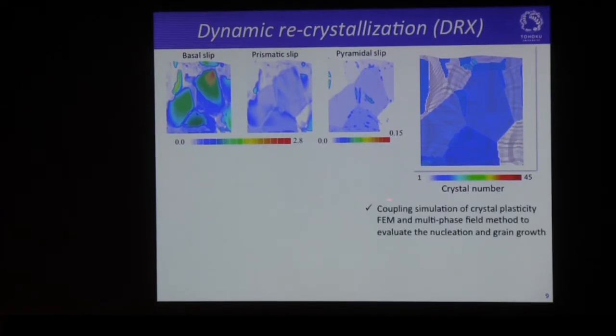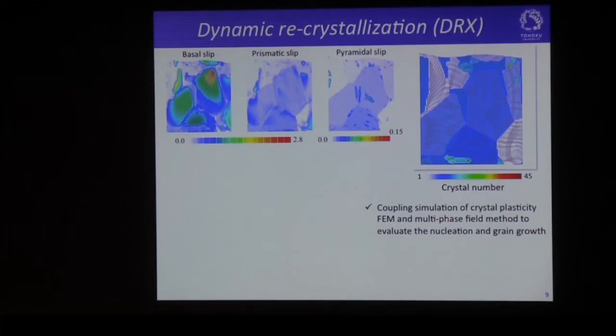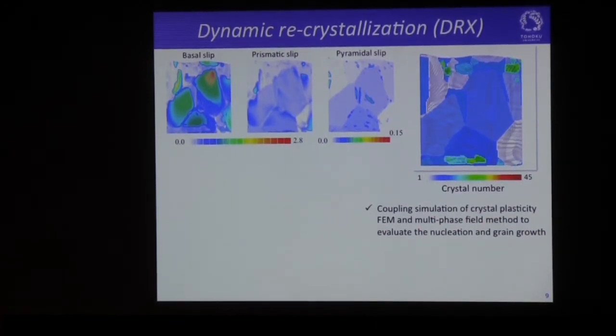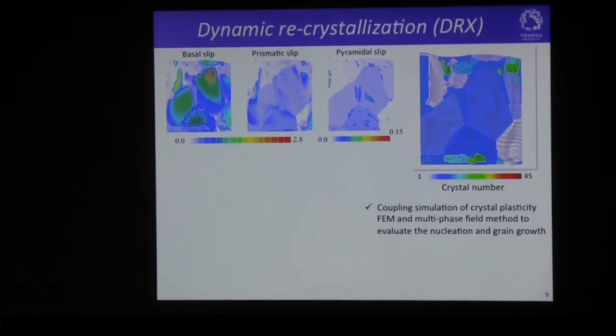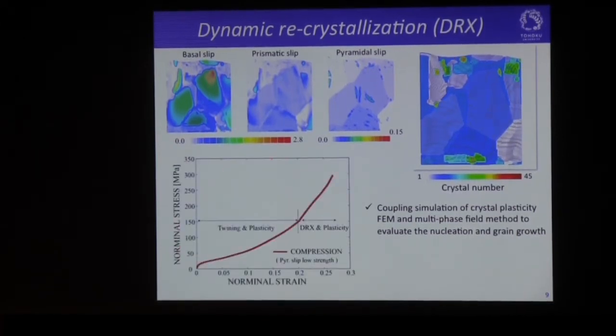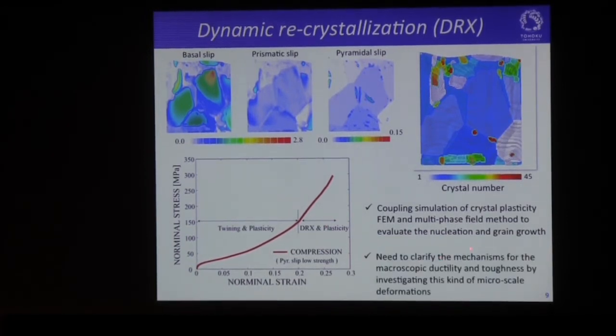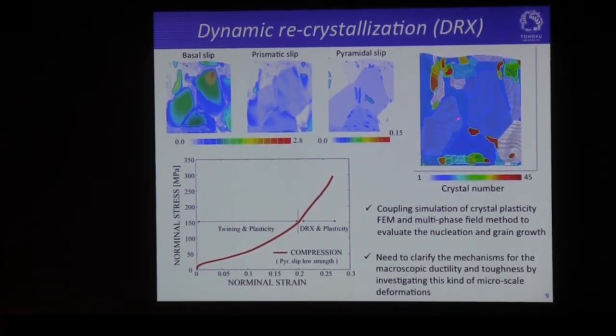Okay, we performed coupling simulation of the crystal plasticity finite element method and also the multi-phase field method in order to evaluate the nucleation and the grain growth, like this. At the same time, we could have this type of macroscopic stress-strain curve. Okay. So from now on, we have to clarify the mechanism for the macroscopic ductility and toughness by investigating this kind of microscale deformation and also the macroscopic response here.